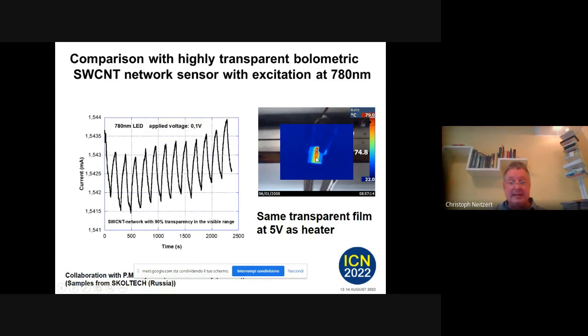Again, you can use them as a heater. That's transparent. That is 90% transparent, by the way. And you see, it's a bolometer, but it suffers in some way also from cycle stability. And that is why people want to use matrices that can stabilize, because carbon nanotubes alone, of course, are sensors in every way. You have adhesion, you can use them as gas sensors. Everything is changing the conductivity. So better in some way to put them into an encapsulating matrix.